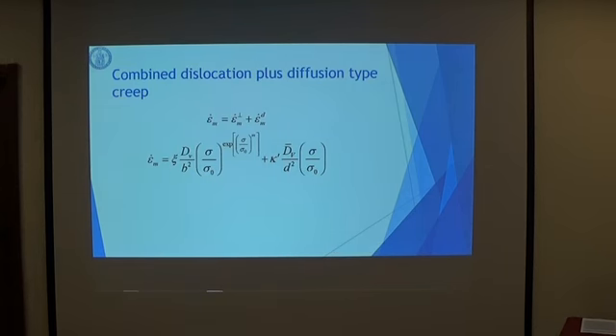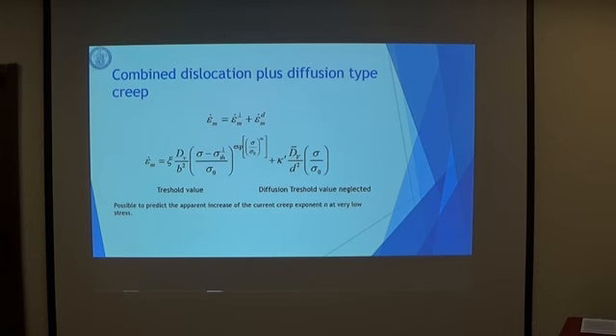If now we consider the contribution of the dislocational mechanisms, we can see there is an explicit dependence of the exponent on the stress level, as I was saying before, while for the diffusion part, the exponent is equal to 1. And it's also convenient to consider a threshold value of the stress below which the mechanism of dislocation and diffusion is inhibited. Here we consider just the one related to the dislocational contribution because the one related to the diffusional one is very low.